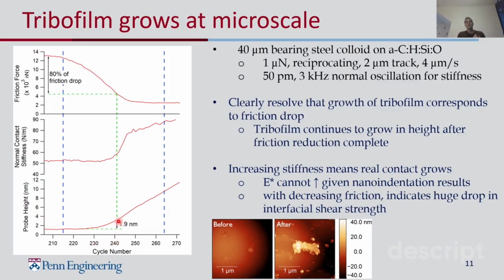So what this is telling us is that while the tribofilm provides a lot of lubricity in the system, this lubricity is a near surface effect of the tribofilm. So the fact that the tribofilm grows to 30 nanometers, the bulk of that tribofilm is not participating in lubricating the surface. It's only the top 2 nanometers or so that provides the vast majority of the lubrication. And so for future studies to try to understand where this is coming from, you only need a thin layer of tribofilm to drive most of the lubricity.